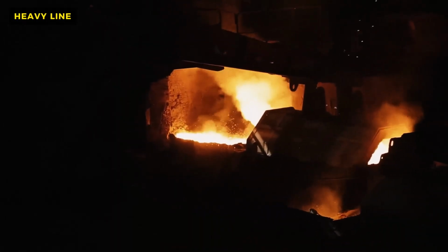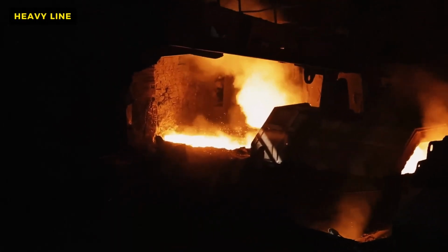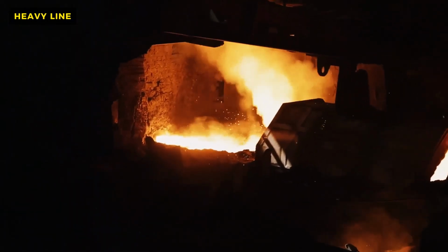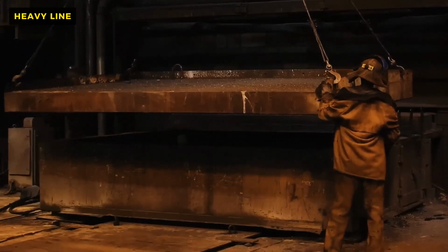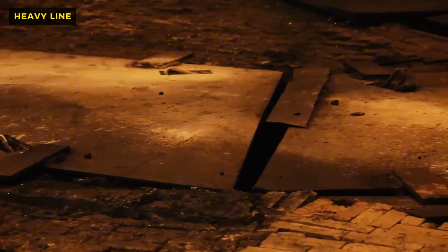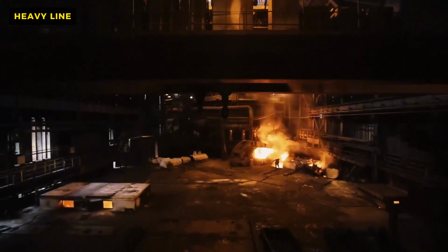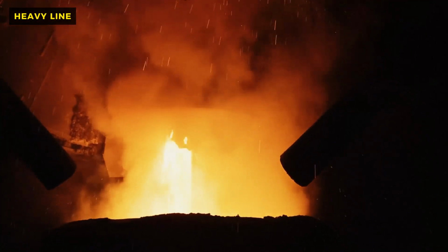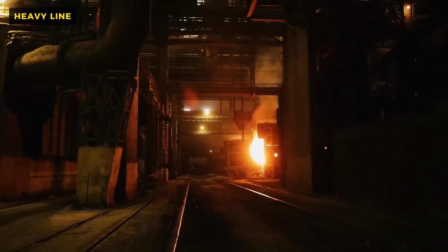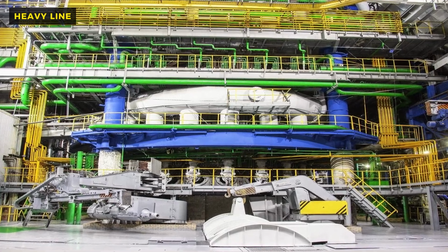If the cooling water were to fail, the steel shell would soften and rupture within minutes, unleashing a river of liquid fire. Every few hours, the furnace must be tapped. This takes place on the cast house floor, a cavernous, dark space illuminated by the orange glow of the runners.